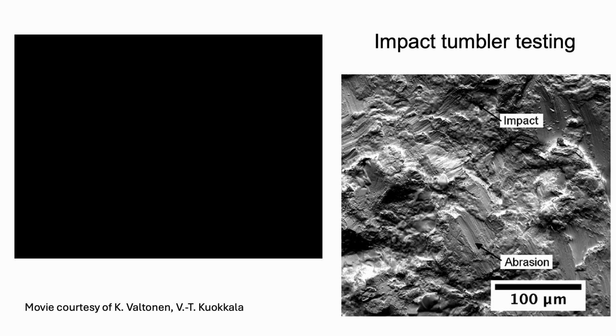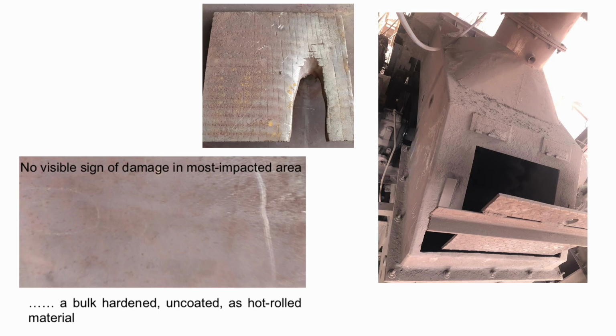Now, of course, when you do experiments in the university, they may not be representative of what happens in real life. So we installed this steel in a location in Tata Steel where they had significant problems with minerals falling onto a particular steel plate, which was coated with hard-facing alloy. The hard-facing alloy is a very high chromium and carbon alloy containing large M7C3 particles, and you can see it here. The hard-facing alloy is deposited by welding. So all that adds to expense, and it wears out into the damage that you see in approximately 3 months.